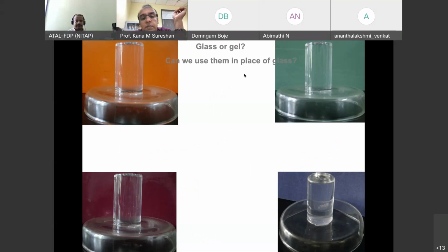Another important point is, anyone looking for a glass substitute, soft glass, a jelly type of glass substitute, two important things are transparency or transmittance, and the other one is refractive index. Water is also very transparent, but you cannot make a glass substitute from water or ice because the refractive index of water is so poor. The refractive index of glass is 1.5 and the refractive index of most oils is also 1.5. So if you make an oil gel, that can be a possible glass substitute, provided it is transparent.